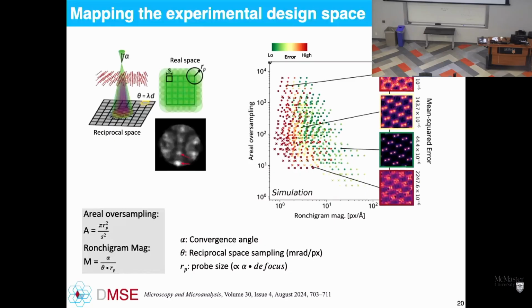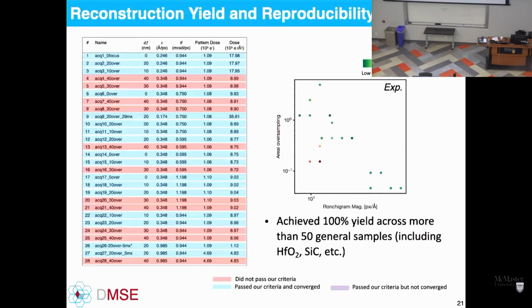And by plotting these out, we essentially have a region here, roughly a line there, that will give us reconstructions essentially every time. The red dots that bleed over here are just small convergence angles that make convergence more difficult. But we really have a line, essentially, of go, no go of whether or not your data is going to reconstruct, based on the convergence angle, how finely you've sampled in reciprocal space, that's this theta, and how big your probe was in real space. From these three variables alone that build into these parameters, it really does have a very good prediction capability.